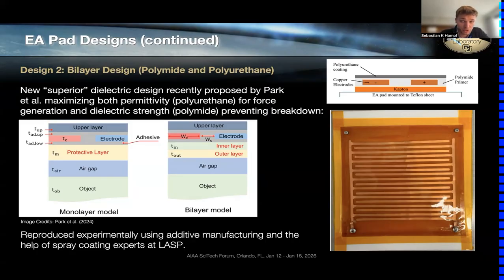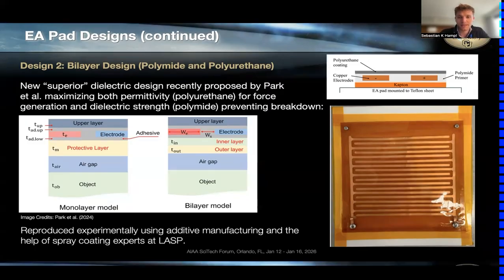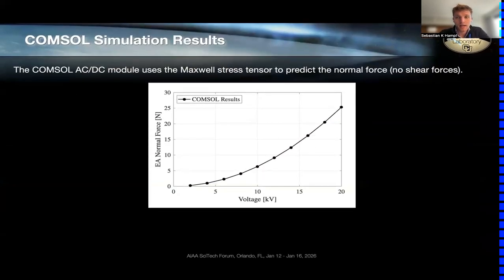And the computational study that proposed this design has found these pads to have superior performance, but it was never experimentally tested. So looking at the COMSOL results, we used the standard approach, the AC/DC module in COMSOL, and a Maxwell stress tensor to predict normal forces for our pad design. So we input exactly the geometric parameters that we had in the manufactured pad to have best comparability with experimental results. COMSOL is not able to predict shear forces.